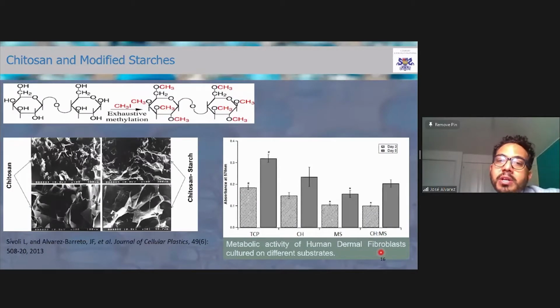Then we started working with chitosan and starch, and this was very interesting because I met this researcher who worked with starches. She does all starches for food applications, food science. And she said, I have this methylated starch that doesn't work very well for our applications, but when it dries, it forms this very rigid plastic. So I said, well, let's combine it with chitosan and see if we can do something about that. The problem initially was that the plastic was very soluble in water, and this is why we incorporated chitosan.